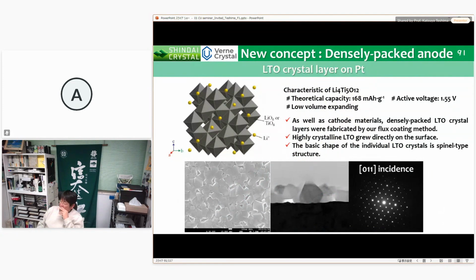These are the crystal structure and TEM images of LTO crystal anode materials, one of the anode materials. As well as cathode materials, densely packed LTO crystal layers were fabricated by our flux coating method. As you can see, highly crystalline LTO grows directly on the surface, and the basic shape of the individual LTO crystal is a spinel type structure, as shown in these TEM images.